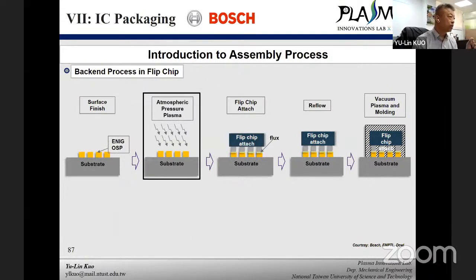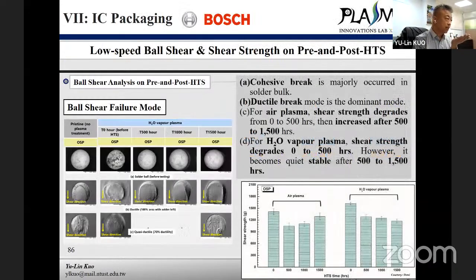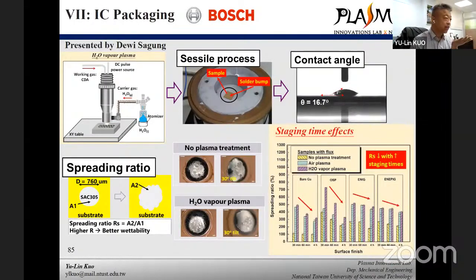We try to use plasma on the Bosch sample because we use air. The substrate is copper. So the copper will be easily oxidized, but it's only partially oxidized on the surface. So we use the plasma to treat the surface, and we can make the surface uniformly oxidized from copper into copper oxide, which means a uniform copper oxide will be formed on the surface.